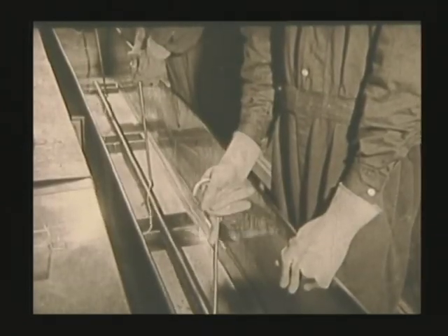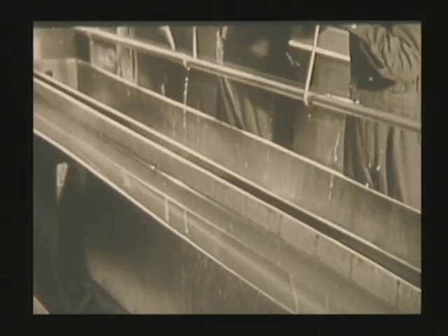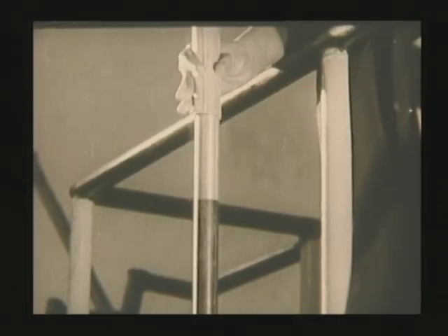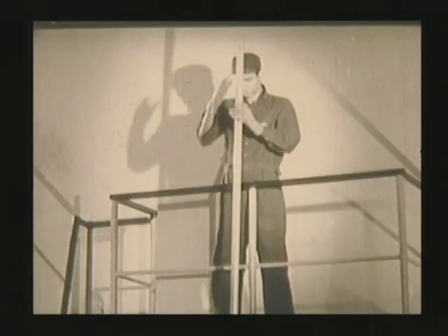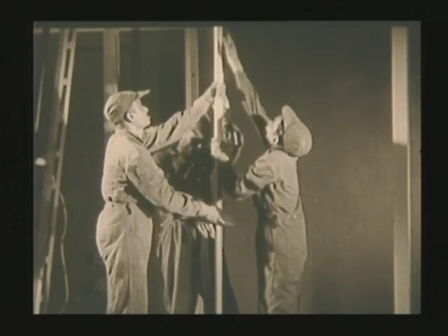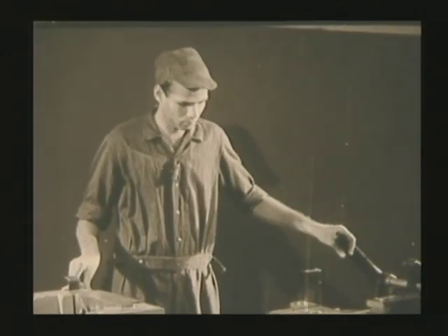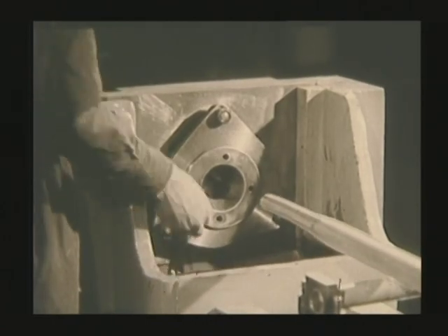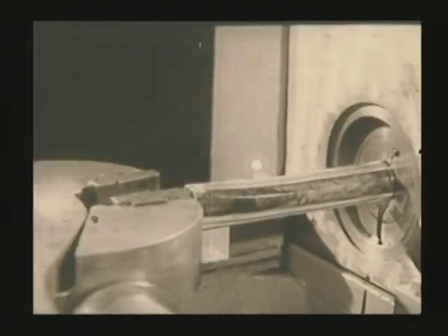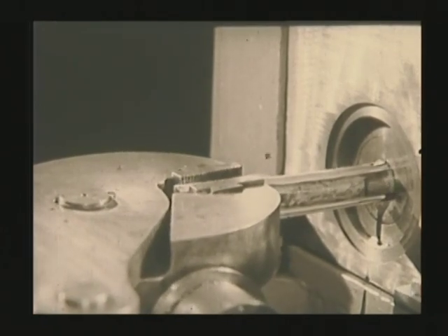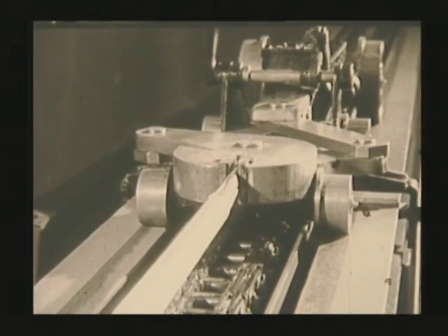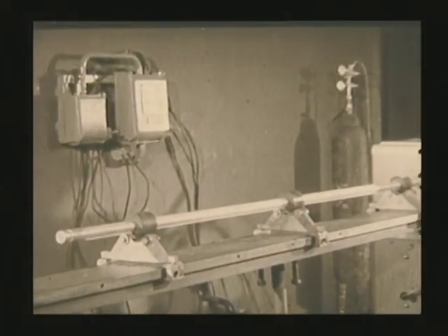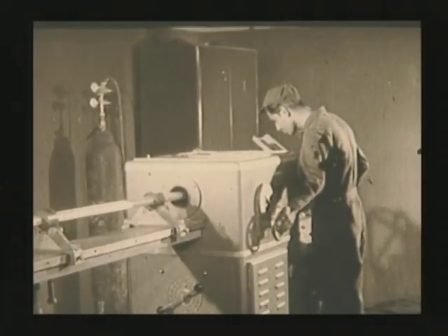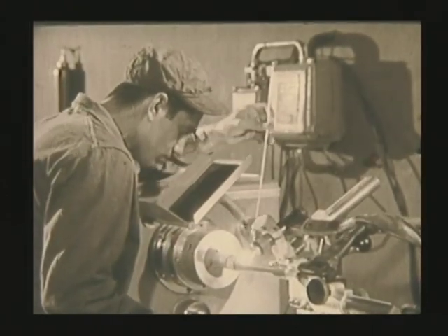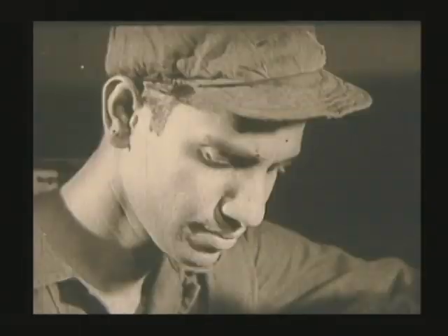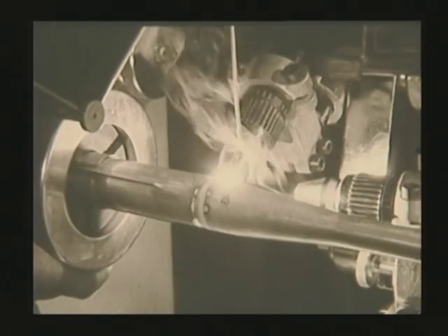The rod is then degreased in trichloroethylene and dried. An aluminium sheath is slipped onto the rod. The assembly is drawn through a special die on a draw bench to ensure firm contact between the aluminium sheath and the uranium rod. The ends are then hermetically sealed by argon arc welding. The uranium is thus completely clad in the aluminium tube.